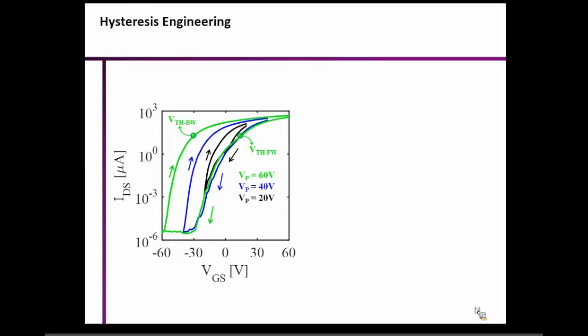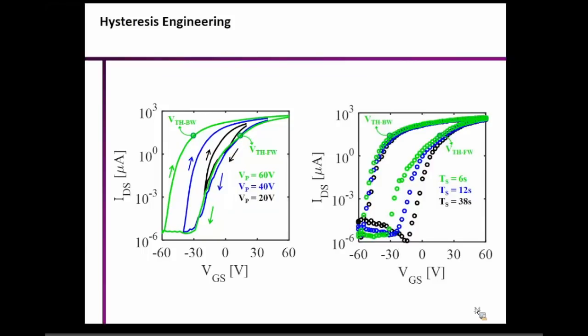And what has happened over the years is that we have made silicon devices so nice that we have separated these two effects. Now these effects come automatically with this 2D material, and you can see that depending upon the drain voltage or the gate voltage that you are applying, your hysteresis width changes, which means the device has a memory. It remembers whether you have applied minus 60 volts or minus 40 volts, and that's how its characteristics change. It's the same with whether you do a slow sweep or a fast sweep: your hysteresis also changes. So depending upon the temporal and the voltage input, you can change this.